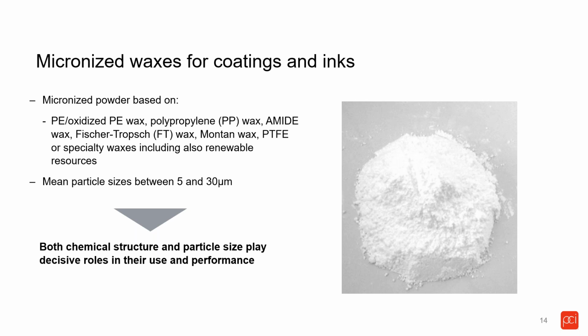So for powder coatings, we actually would use both types. But the micronized waxes are going to be those same variety of waxes that I showed on the previous slide: polypropylenes, polyethylenes, modified and unmodified waxes. Typically, the D50 is going to be more 5 to 15. We do have a few that are on the larger end, especially for texturing in powder coatings. But the key here is that it's not only the chemical nature and the chemical structure, but also the particle size distribution that are really going to play a decisive role in the performance in coatings and inks.